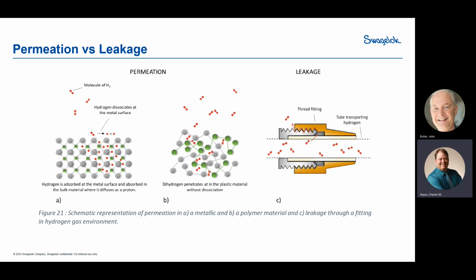And then it can go in there and start playing around and cause a variety of problems in lower quality product. So if the bonds between the molecules are not good, it can help break those apart and then have something to latch onto when it breaks apart a molecule and it's got an open electron field to connect to. That's a very basic way of saying this is how it starts to break things down. It can work at the end of cracks, in hydrogen-assisted crack propagation, and help those cracks open up as those molecules are breaking apart at the bottom of the crack. It can go in there and help it crack faster. So that's what we're understanding today of the mechanism that's taking place.